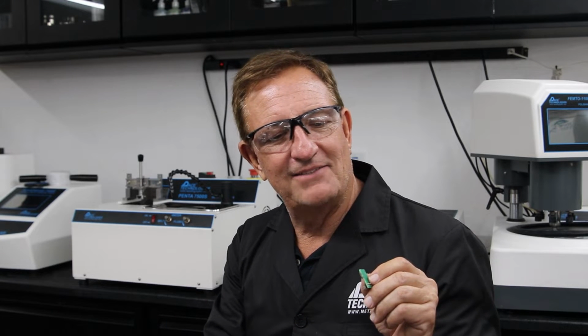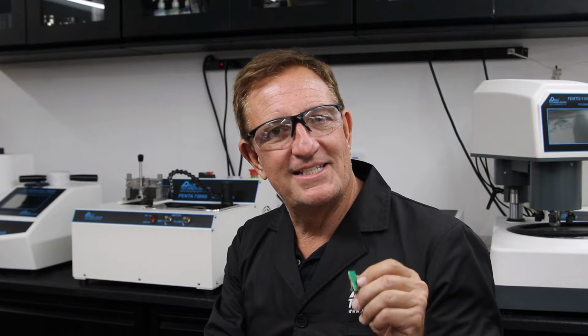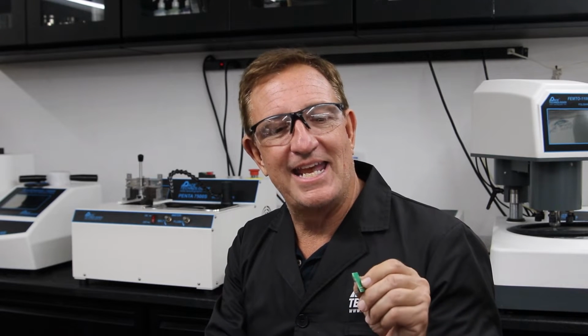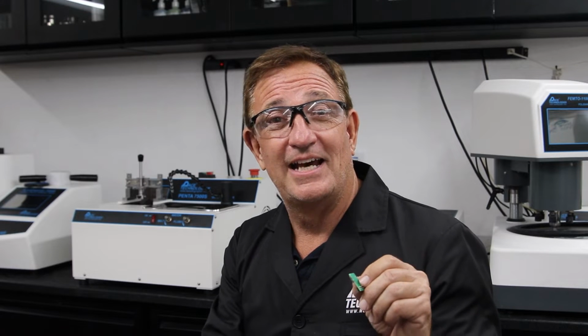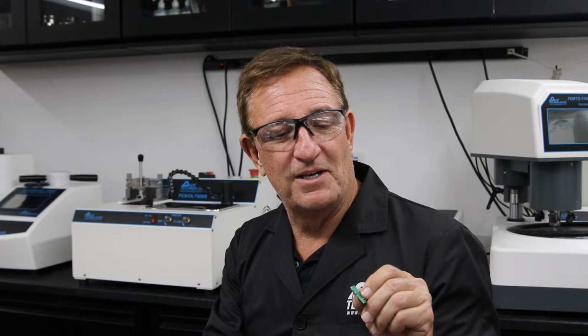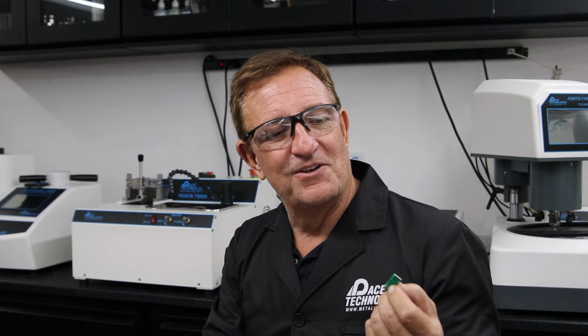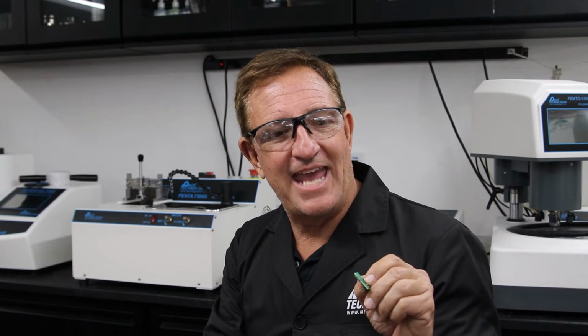The idea of how this works is essentially we'll pull a vacuum, we'll pour the resin onto the sample while it's still under vacuum, and then we increase the pressure. What this does is it pushes the resin basically into the void. To enhance that even more, you could actually cure it at a higher pressure using a pressure chamber as well. But for vacuum impregnation, it's very useful for filling in gaps, porosity, and other things where you want to have more structural edge retention before you go to the grinding and polishing operations.